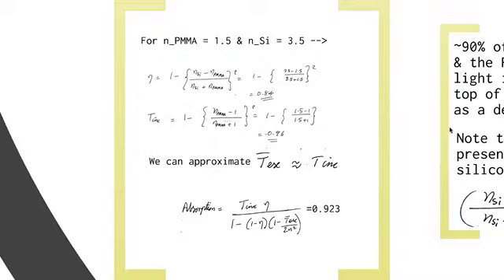T incident is what's coming into the plastic. That's 96%. Remember, 4% is lost. And T bar escape and T incident, they're going to be approximately the same. You plug in all this stuff. This will cancel out. You will end up with something like 92. Now this is very nice because if you do nothing, this number will look like 70%.